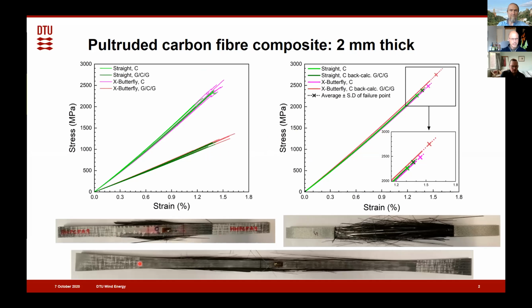Now we could try to do that also for the butterfly shape, and here I only show the results for the extra long butterfly shape. So this is the same shape as before, but now again here we have put a constraining layer on top of the material, which is so thick so the sample will survive the failure of the carbon fiber. And now we get the purple lines here, the purple and red line here. So the red is for the constrained case, and the purple here is for without any constraint layer on our